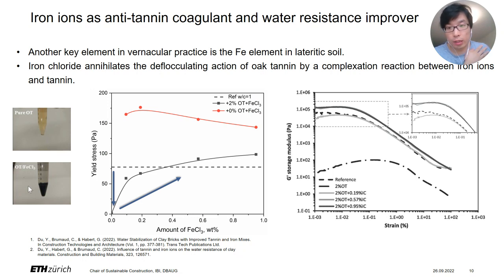As you can see from the picture here, after putting iron chloride in the tannin solution, we saw some precipitate form in the solution. That means the tannin can be precipitated out of the solution by the iron chloride. And in the meantime, the yield stress of the paste is getting higher. We can see this more clearly with the oscillation sweep curve.